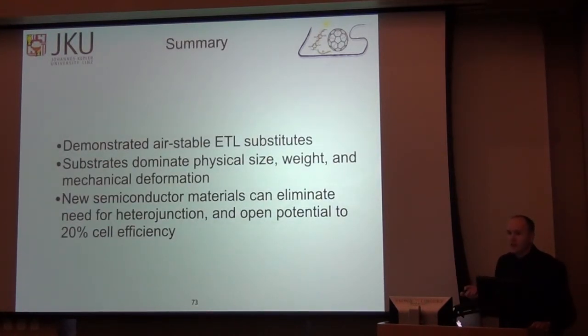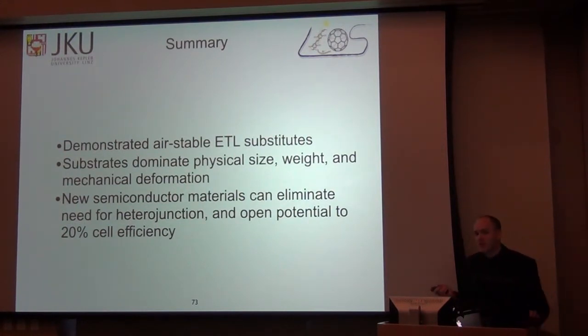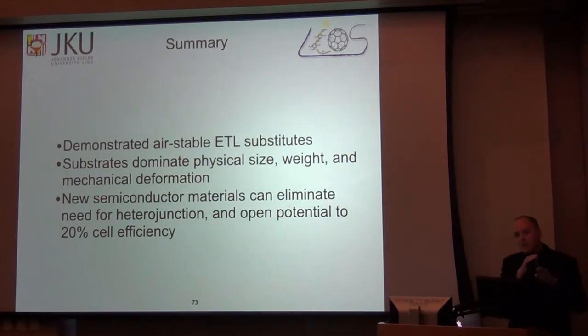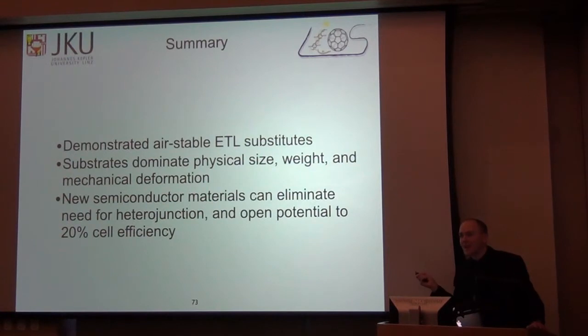We've changed the substrate to change the mechanical properties, and we see new semiconductor materials that show that if we can arrange or control the intra- or intermolecular interactions in ways other than simply putting them down and having them pack in a van der Waals configuration, then we might be able to use organic semiconductors to make solar cells. This solar cell was about 1% efficiency, but we might be able to approach 20% if we can get rid of that heterojunction offset. And that is going to be key.